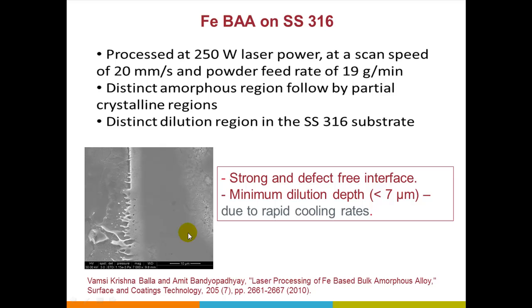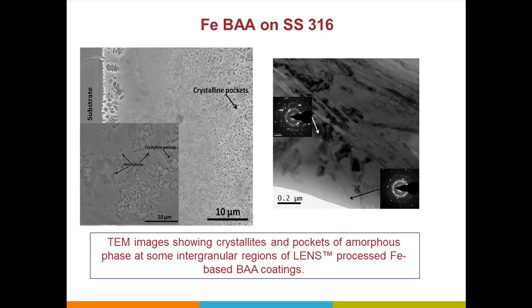So this is our coating. This is the transition zone, only about 7 micron, and beyond that on the right hand side is the bulk amorphous alloy, left hand side is stainless steel. Again, 250 watt laser power was good enough for us with this particular chemistry, you don't need a whole lot. Scan speed and powder feed rates are 20 millimeter per second and 19 grams per minute, and we could build actual bulk structures with this as well.